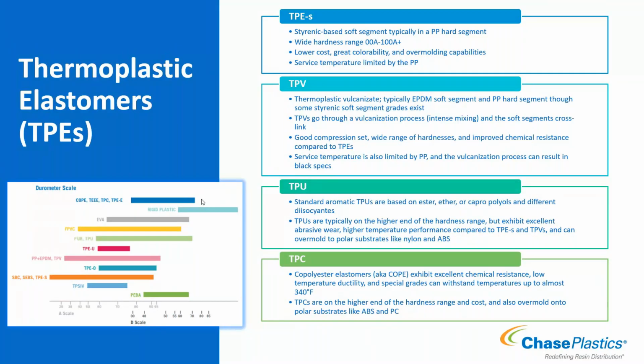Good wide range, not as wide as styrenic TPEs, but still a decent range of hardnesses available. My service temperature is still going to be limited by the propylene, so I don't see a huge improvement in continuous use temperature. You will see an improvement in compression set though, and resilience, because of the cross-linking.